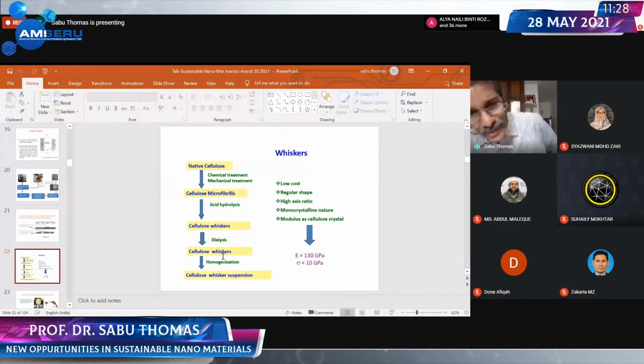What is the property of this material? See, the strength of the material is 10 gigapascals. Modulus is 130 gigapascals. What's the typical modulus of polymers? The typical modulus of polymers is in the range of 2 or 3 gigapascal. Look at the modulus of nanocellulose. That is why polymer technologists are really interested to put this material into polymers to reinforce polymers.